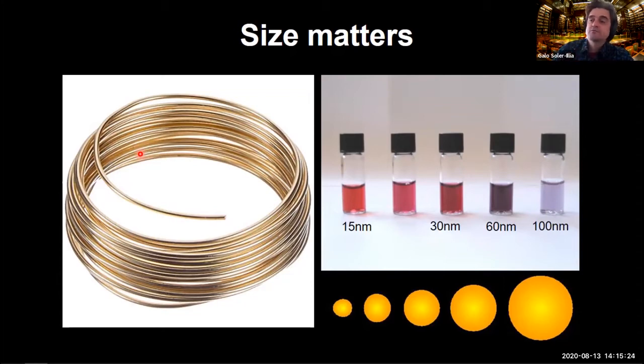But what happens when gold is smaller? These flasks here contain solutions of golden particles. But these particles are not golden anymore. It's observed that, for example, if you have a gold particle which is small, about 15 nanometers in diameter, it presents a red color. Whenever you increase the size a little bit, you get deep ruby colors, and then when you go to 60 nanometers, you have a purple color. And then when we go to 100 nanometers, you don't have suspended particles anymore, but you can have a kind of precipitate and light scattering. So here you see that all these particles are gold, metallic gold, but the metallic gold is no longer golden, but is red, purple, ruby, depending on the size. This is marvelous.